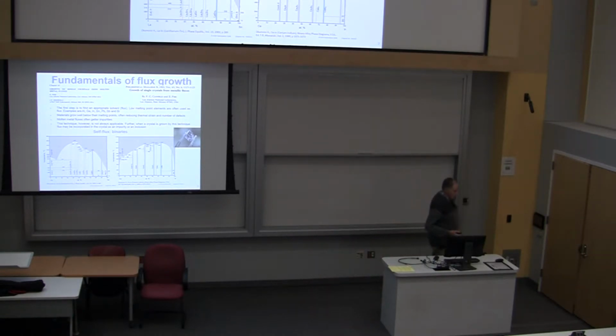Tin melts at a rather low temperature compared to lanthanum and platinum, and this very exothermic reaction happens at some temperature that's maybe around 1,000 degrees or so. If you heat up slowly enough, the tin can dissolve these elements before they get together to react in this very exothermic way. So just something to keep in mind.